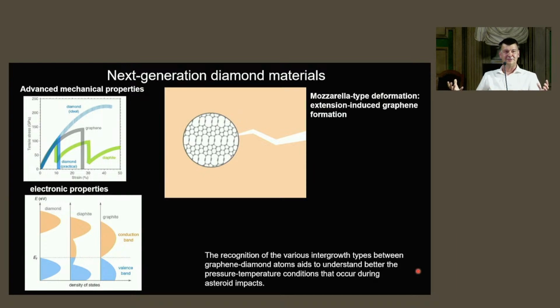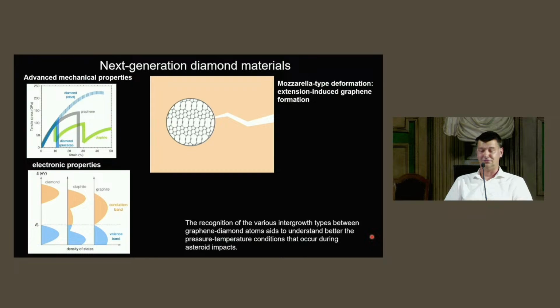So if we consider this diaphite structure, which is contained within diamond, we could engineer a fracture-toughened diamond, which behaves like a kind of ductile diamond. In fact, we gave the name that under tension, these diamonds behave with a mozzarella-type deformation, and as a propagating crack, during extension, during breaking, the structure could absorb the energy of this propagating crack. And calculations demonstrated that this happens as a result of extension-induced graphene formed when we apply extension.